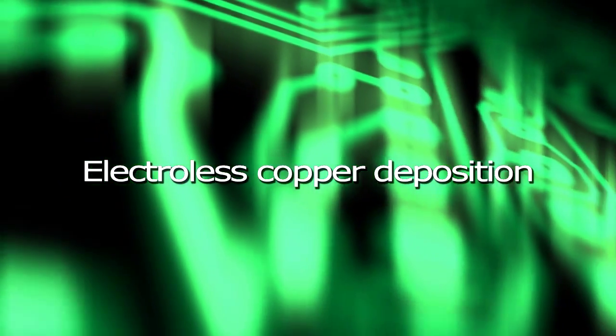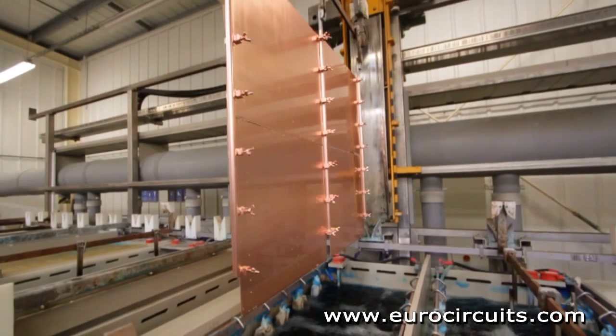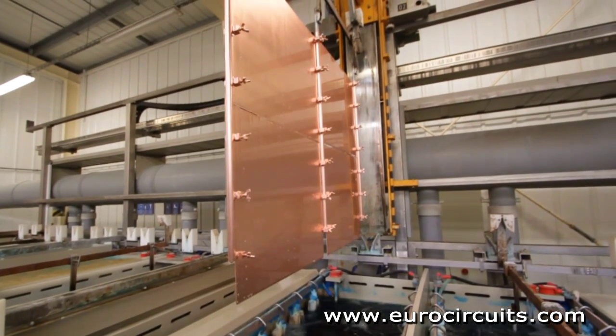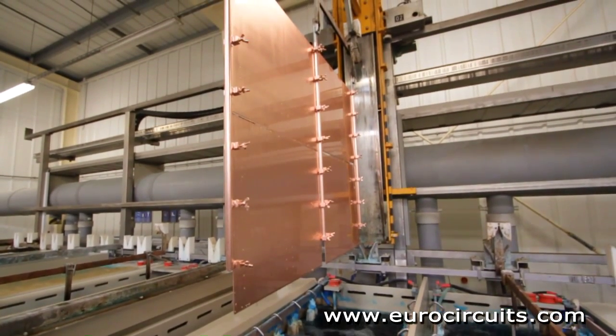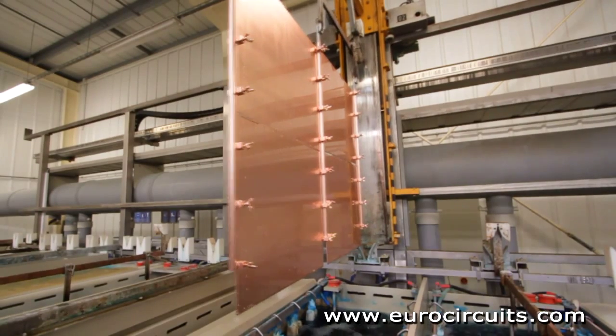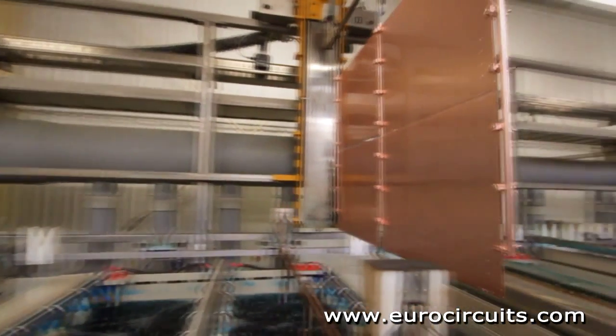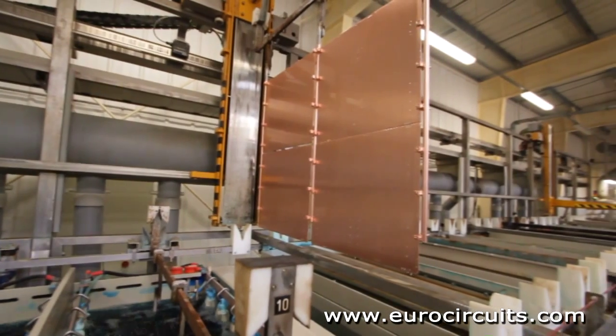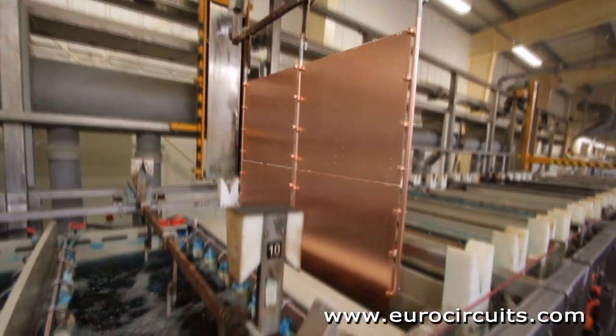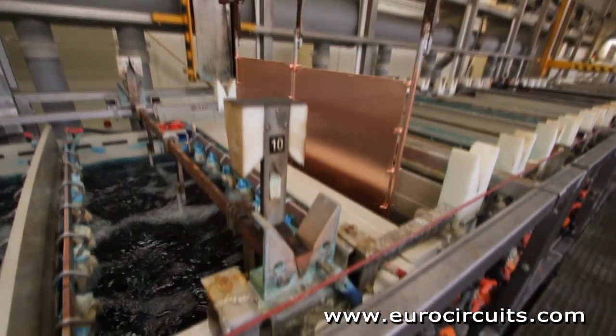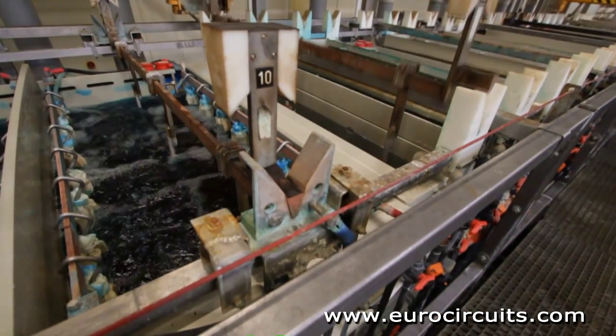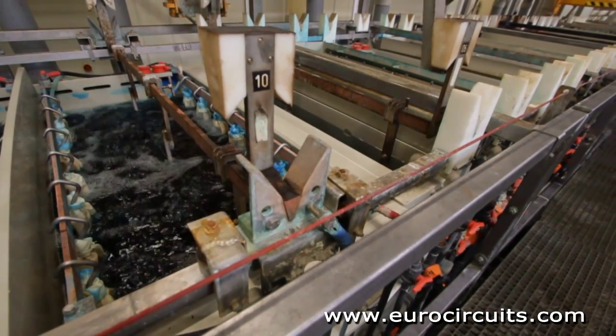Electroless copper deposition. The first step in the plating process is the chemical deposition of a very thin layer of copper on the hole walls. Almost all PCBs with 2 or more copper layers use plated through holes to connect the conductors between the layers. A good connection needs about 25 microns of copper on the walls of the holes.